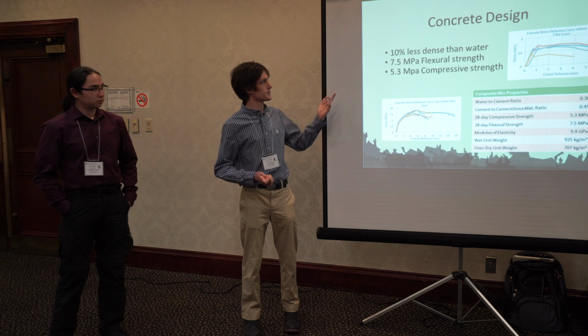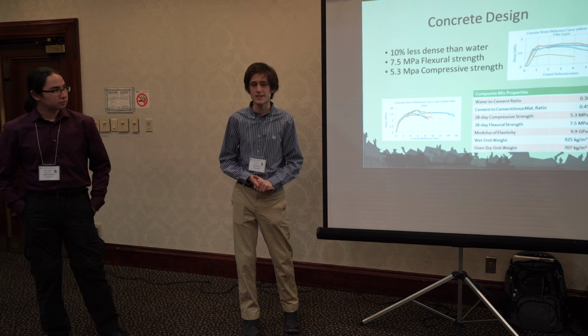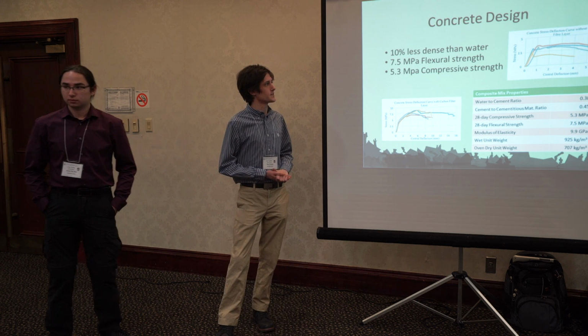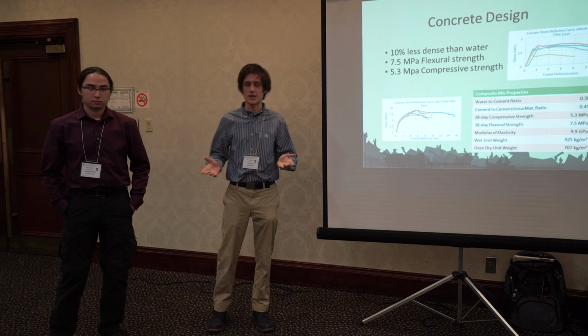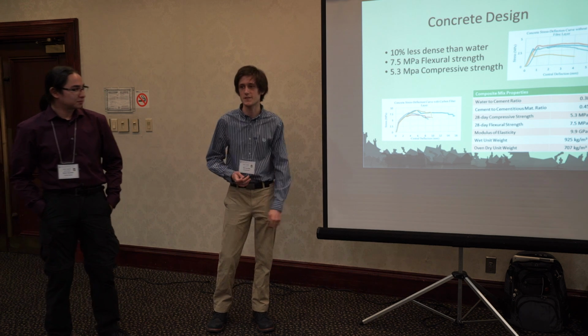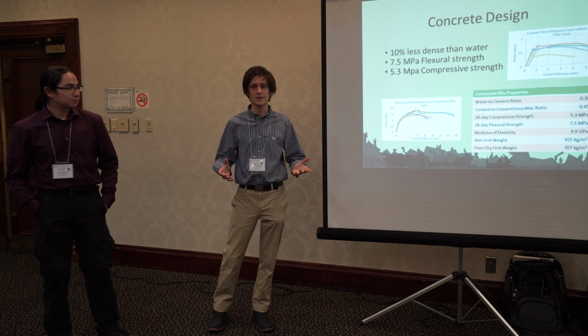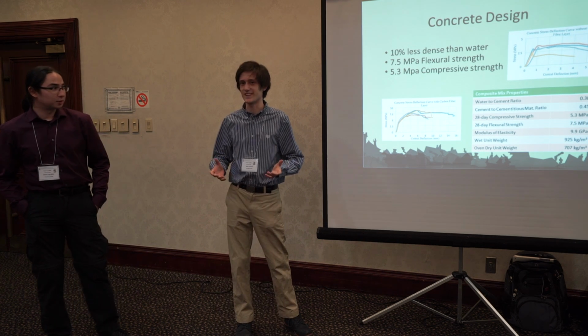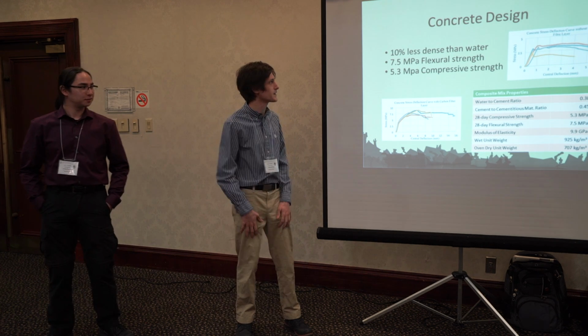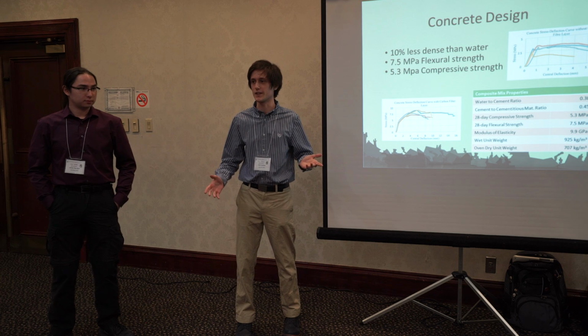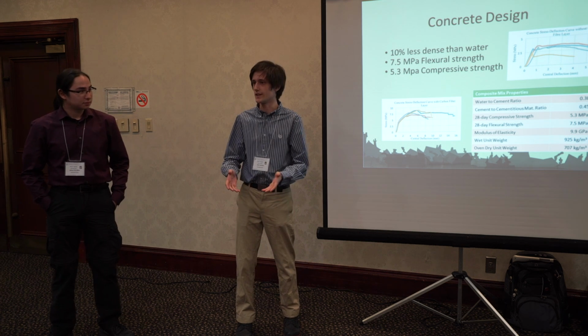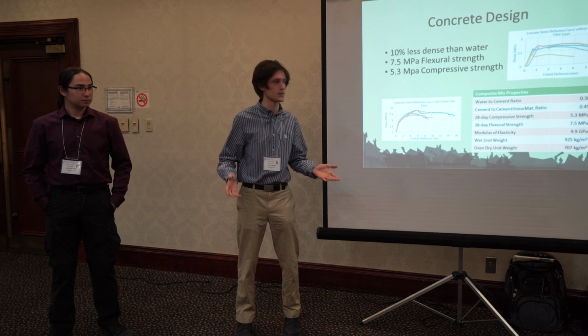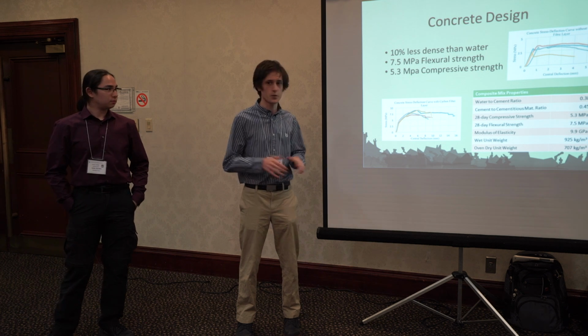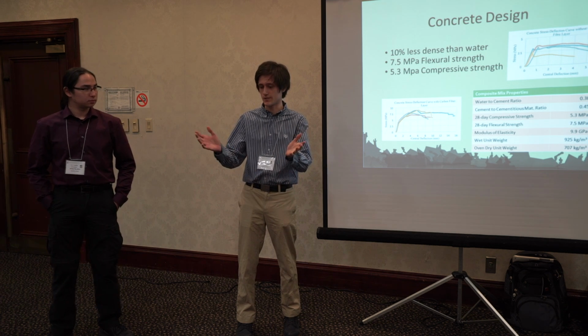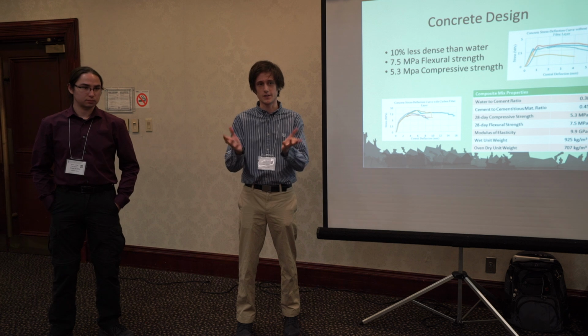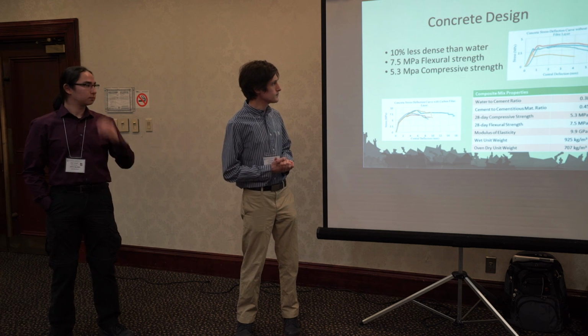On top of that, our flexural strength is 7.5 megapascals, and our compressive strength is 5.3 megapascals. What that means is that we have terrible compressive strength compared to actual concrete. You wouldn't want to put this in a building or anything. It's quite weak if you push down on it, but our flexural strength is actually great. The importance behind this is that a lot of the forces the canoe feels are flexural. Where the paddler's knees are, as well as just the bending of the canoe, really stresses the concrete in this way.